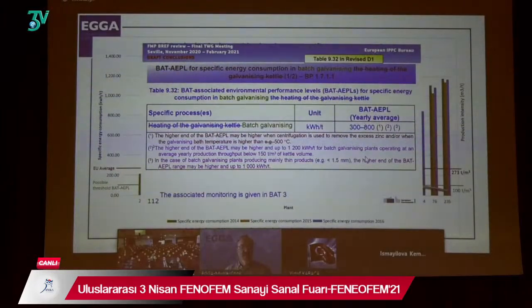You can see in note number 2, the pink is something that we added, or the European Commission added, in February 2021. We now have a footnote which says that the energy consumption can be up to 1,200 kilowatt hours per tonne when the average yearly production is below 150 tonnes per year.